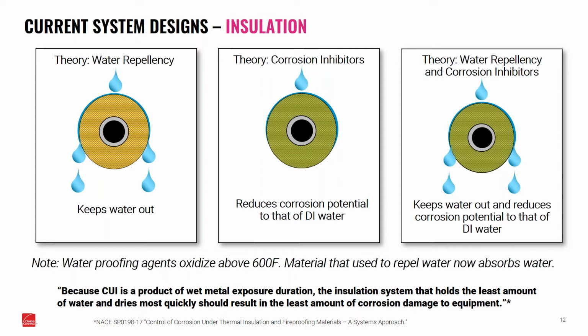One thing to note here, though, and this covers pretty much all insulation types, is that waterproofing agents will oxidize above 600 degrees, and this is regardless of what insulation type it is, with one exception. Foam glass, because it's impermeable to water vapor transmission and liquid water, will keep its water repellent properties up to its 900 degree maximum use temperature. But otherwise, these other additives that are used with these other products for water repellency will burn off at about 600 degrees Fahrenheit.